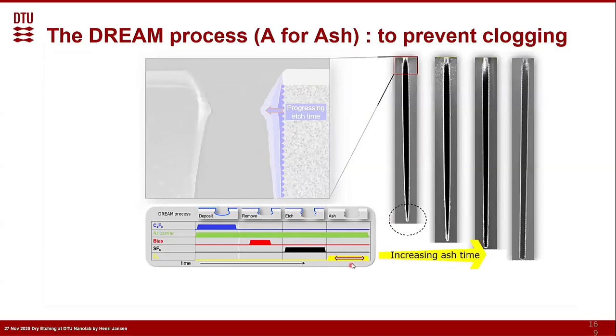So before that, if we would not do this at all, then because it is closing at the top, the trenches are getting smaller, and therefore also at the bottom it's getting smaller. So you get a very nasty positive taper, and it might even stop at the moment where it closes. But now if you increase the oxidation, so after you have done, let's say, in every cycle we knock in an extra oxidation step to etch it away, then you can remove that one, and therefore it stays open, and you can see that after doing this, with the dream process, it just stays nicely straight.